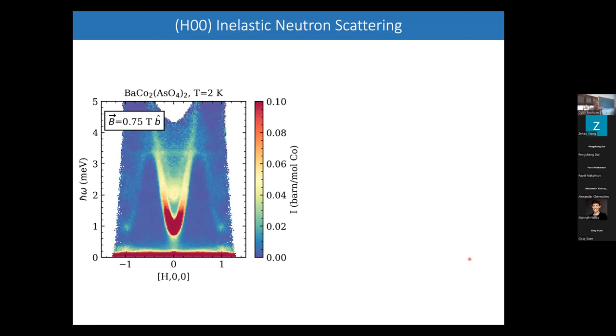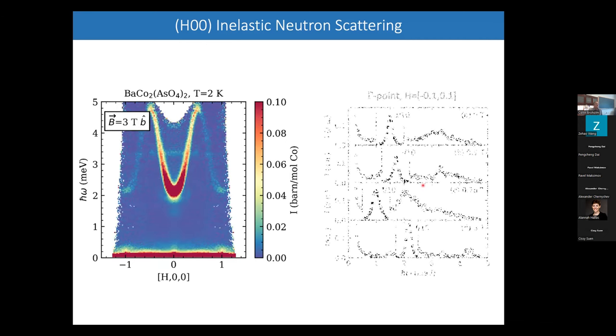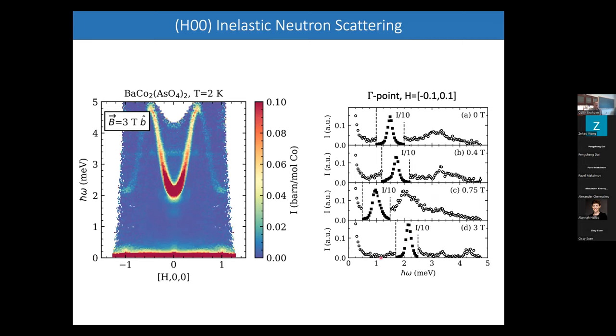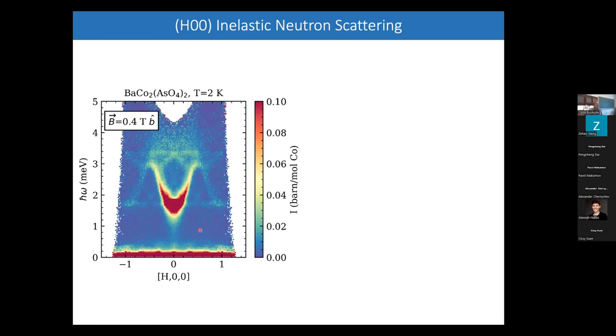Actually, this particular thing kind of steps over the critical field of 0.55 Tesla. Okay, so it's a very quick decline of the gap at that gamma point. Even at 0.75, you can see there's stuff down here. So the critical field is 0.55? Yeah, 0.55. Can you go back to 0.4 then? So you had the data at 0.4, this guy here. This one is pretty close to the transition from the inner side of the phase diagram, and still it's quite gapped. So it's rather an abrupt change.